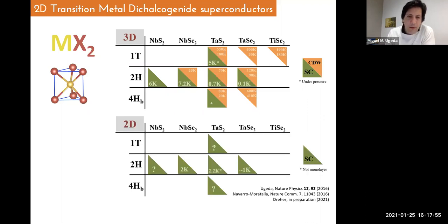In two dimensions, however, as I said, this is a new field, and basically little is known about it. We barely know that, for example, niobium diselenide is superconducting below 2 Kelvin. We have just discovered that tantalum disulfide is also a superconductor above 2 Kelvin. Therefore, for example, the critical temperature increases. In other cases, it decreases, as in niobium diselenide. We don't know why. We don't know the reason behind all these properties in two dimensions.